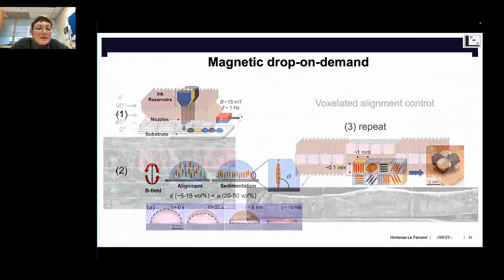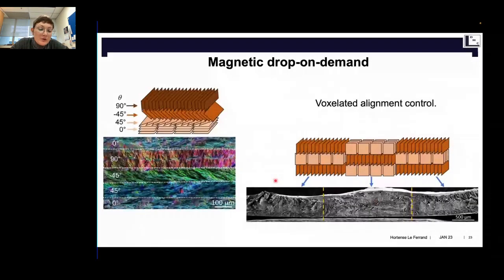So here are some SEM images to show the control. This is a vertical structure where we varied the angle, made with an ink containing the same aluminum oxide platelets as I showed in the part on the microstructuring. So you can see we can really tune the angle as we desire. And we can do it vertically, although we have to take into account that there are some deformations at the interfaces.